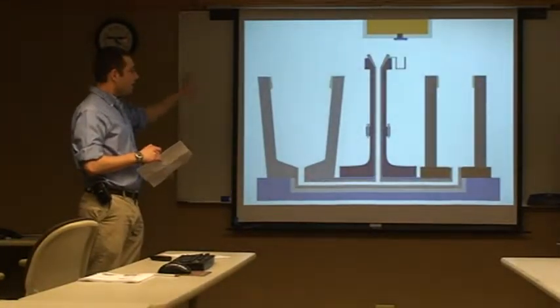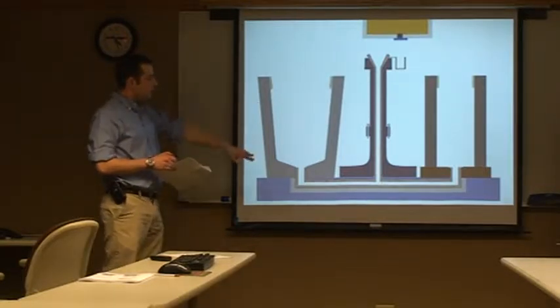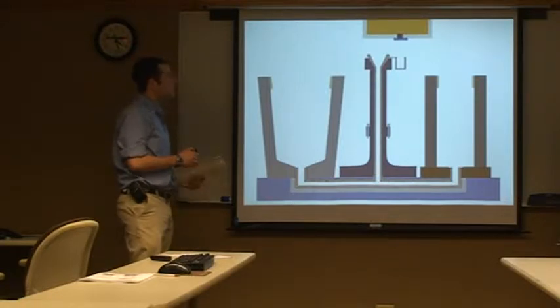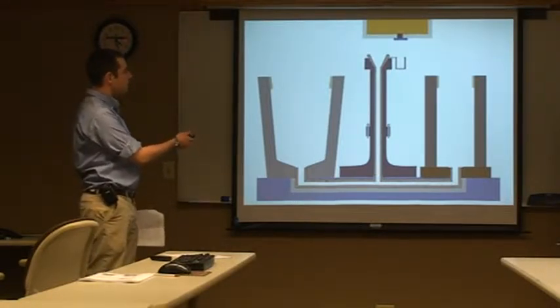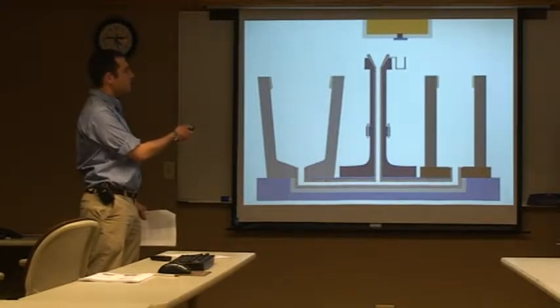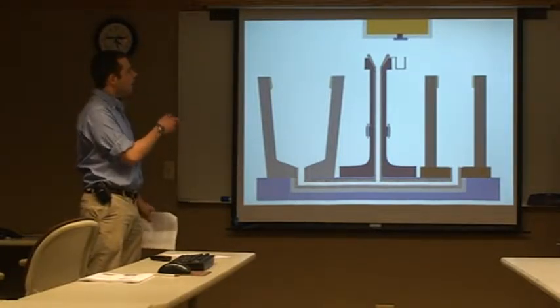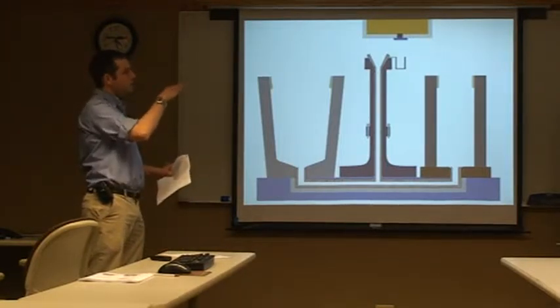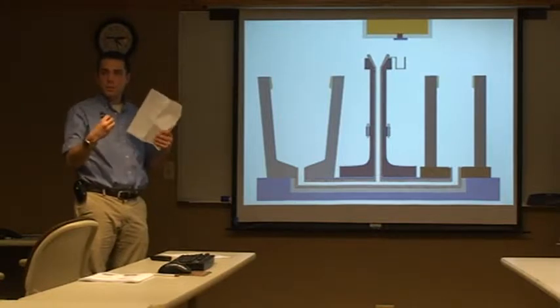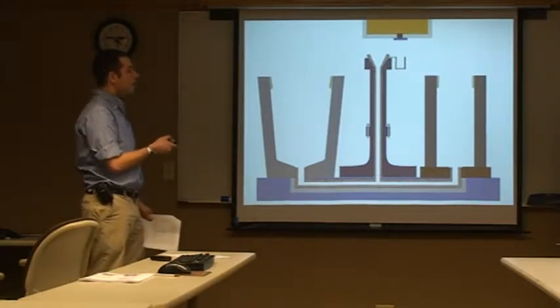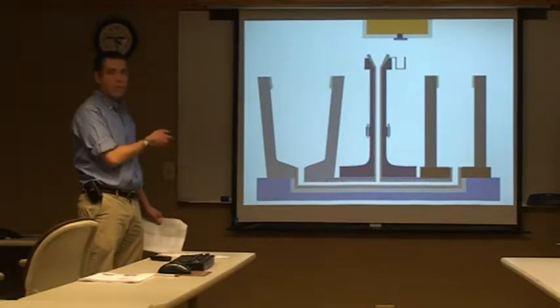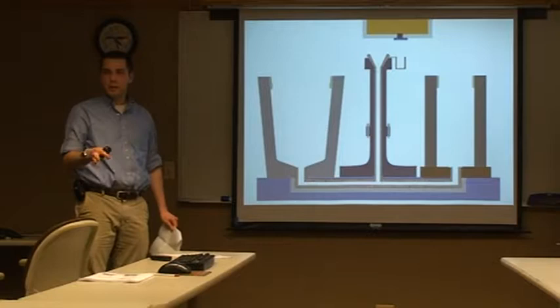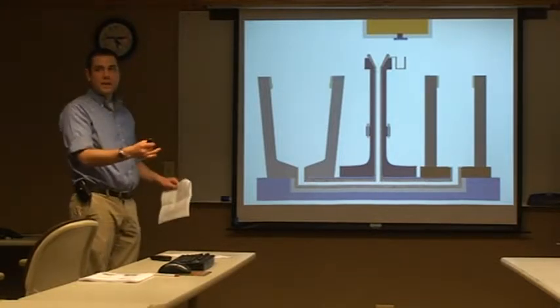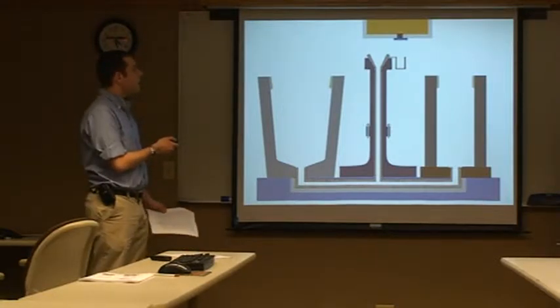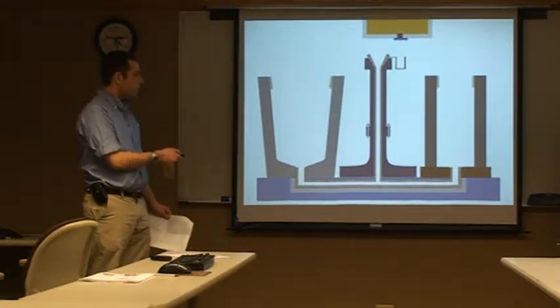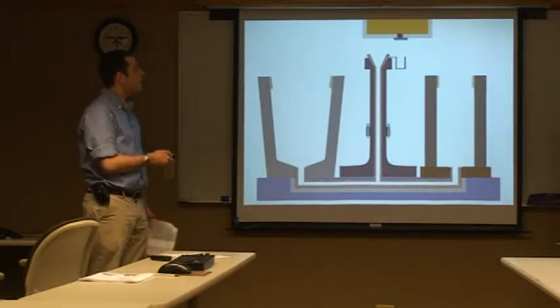So this is another animation of the teeming process, and in addition to seeing these molds filling, you'll see that first it's going to drop the first part of steel in this little canister here. We call these butt canisters, and the purpose of these is that between the liquid steel and the plates that open up at the bottom of the ladle, we put some sand in there, and that's to keep the liquid steel from eroding away the plates while the ladle is going through the various steelmaking processes. So when we open up that slide gate, the first stuff that's going to come out is the sand. And we don't want that to go into our molds because that can cause defects and things like that.